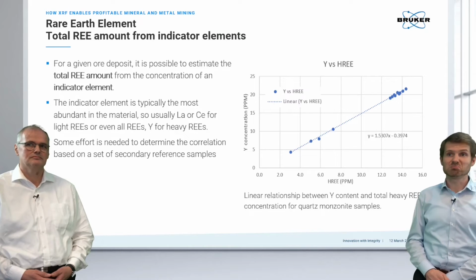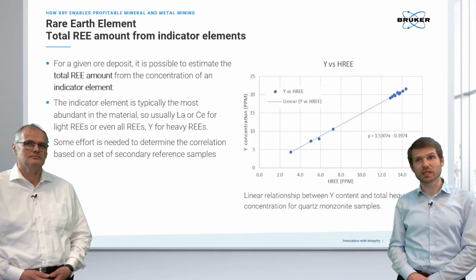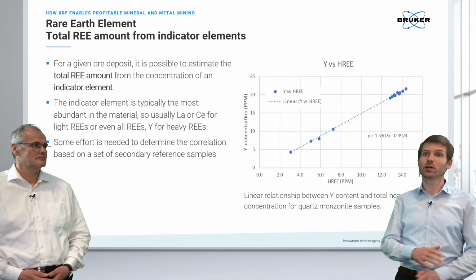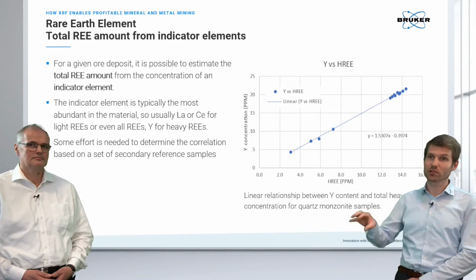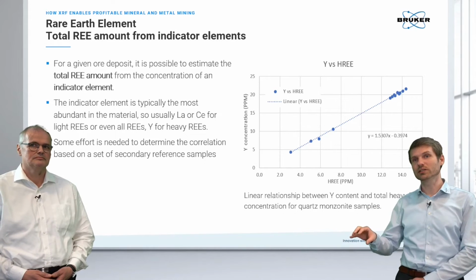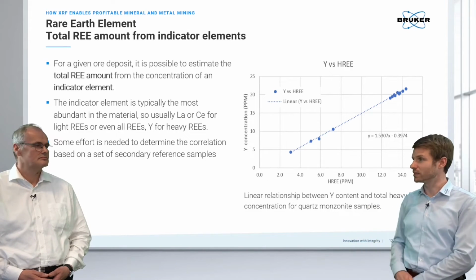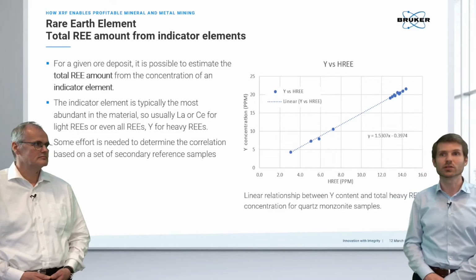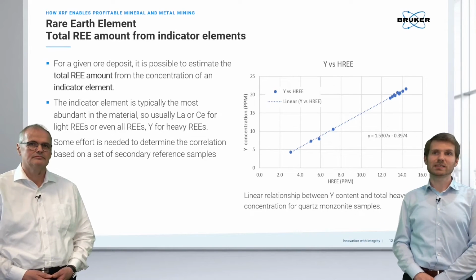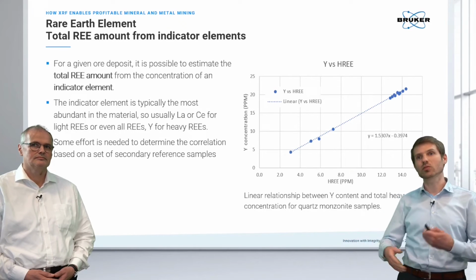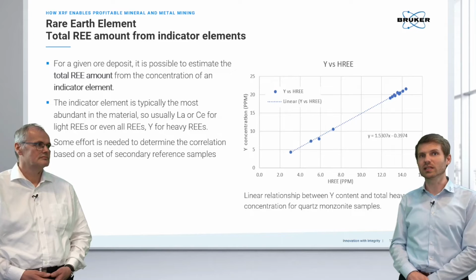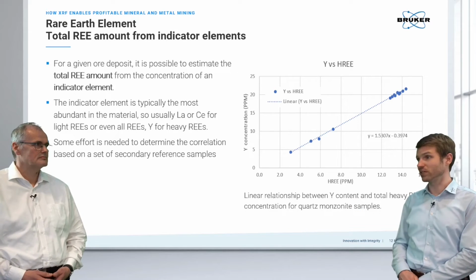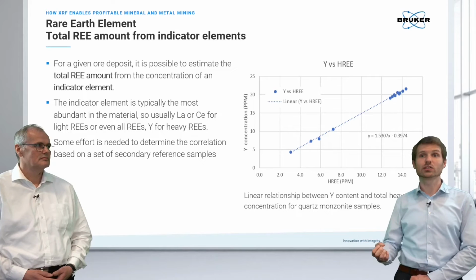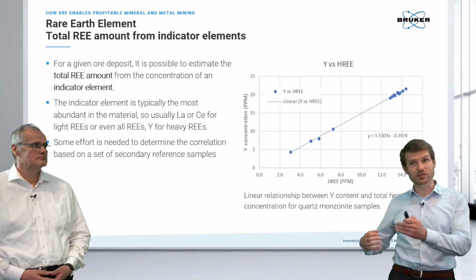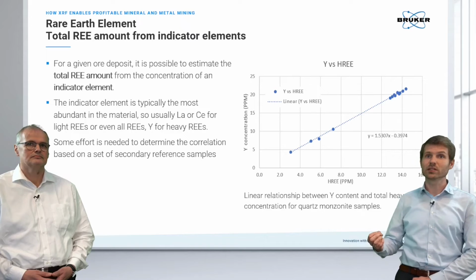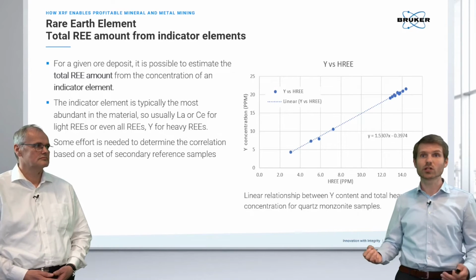Well, first of all, these are relatively low concentrations, but not super low. Then you are dealing with a wide number of elements within these rare earths. You can also separate them by light rare earths and heavier earths. That's a bit based on their natural abundance in the Earth system, basically in the different Earth environments. But because of this relationship that they are all behaving quite similar, you can do a little trick here. And this allows us, especially for exploration work, to get a good assessment of the total rare earth concentration because of their relative abundance being related based on the element which has the highest concentration. So this is a workaround that we can do here.